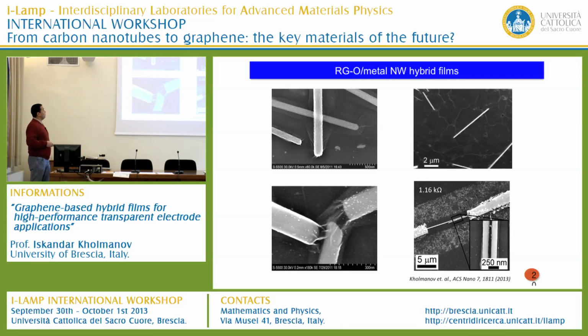These SEM images show some mechanisms of improving the electrical conductivity. First of all, the RGO covers all the surface area of the nanowire films. And if you see here, this kind of nanowires that you can always find when you deposit nanowire films are not connected, and they are not participating in the percolated network. They are just contributing to, and decreasing, the optical transmittance. So this is not efficient when you are using only a nanowire film.